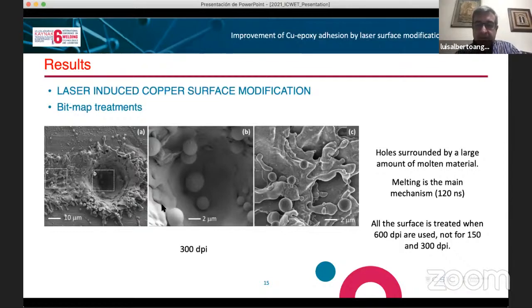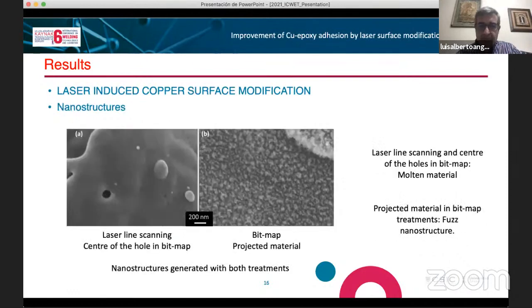When we work with 150 and 300 dpi, the holes are separate, and you see around the holes areas that are not affected by the laser, while when we use 600 dpi, all the surface is affected by this kind of holes. Also, when you look at the nanostructure, you see that with the laser line scanning, and in the center of the hole in the bitmap, you have a very flat surface, while in the area with the projected material, in the case of the bitmap configuration, you have a fuzz-like nanostructure. Okay.